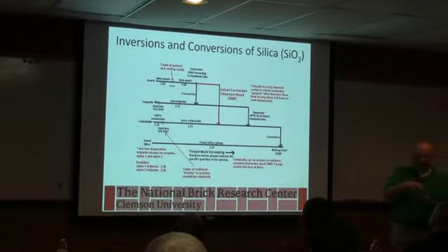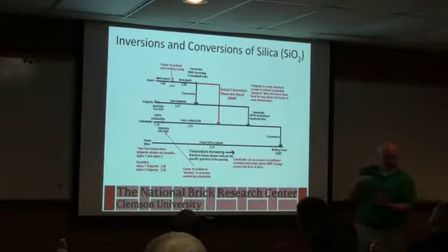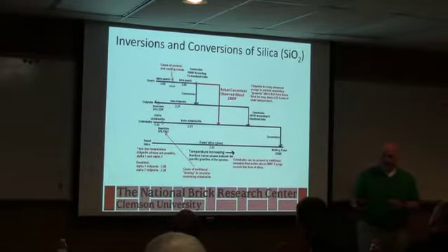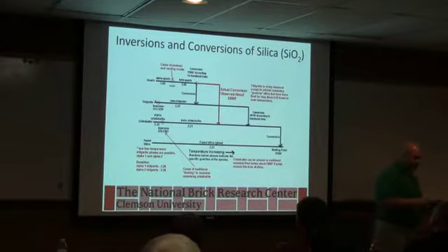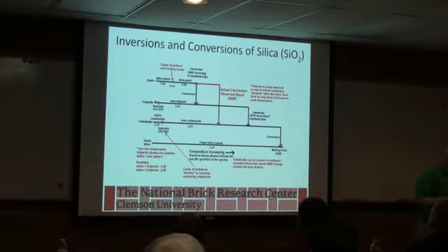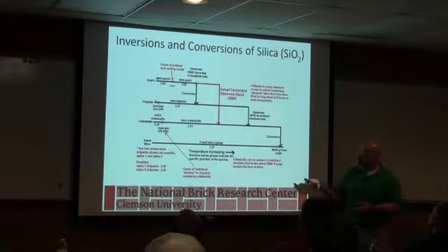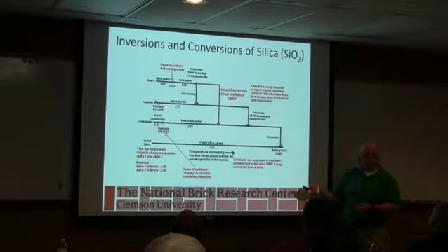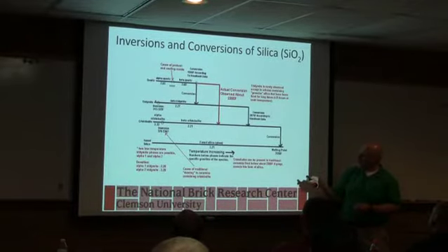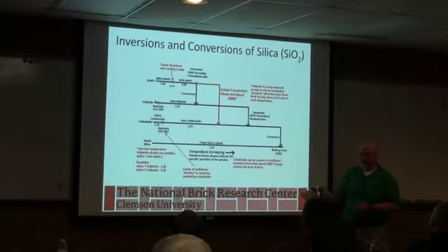Okay, so the quartz mineral gets bigger at that temperature, and this is not something that's kinetically controlled like everything else we talked about. I can go up and come down and up and down and up and down, and it will keep going through that inversion. Now, the theory says you then go to something called tridymite. Tridymite doesn't actually exist. And then if I kept heating, I would take that tridymite and I'd go to cristobalite.